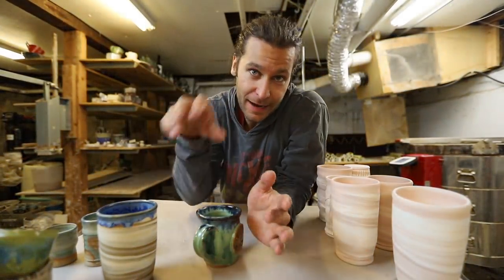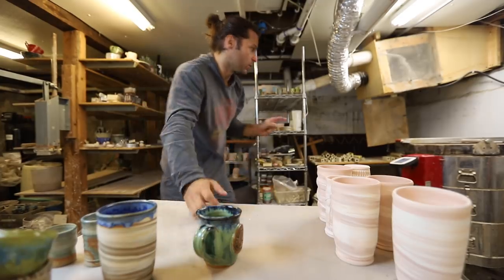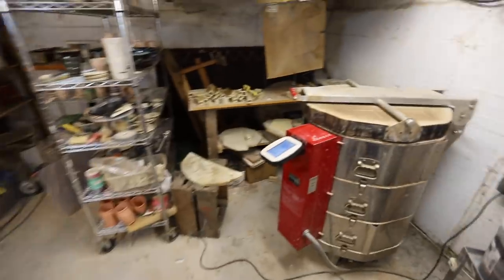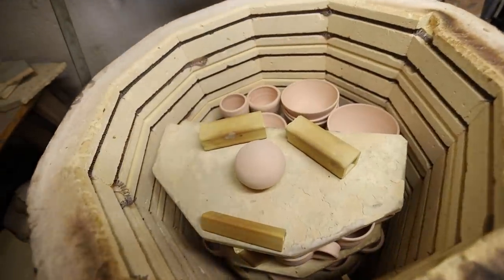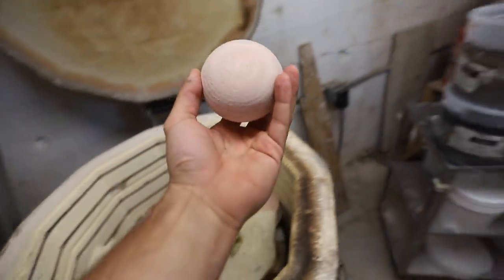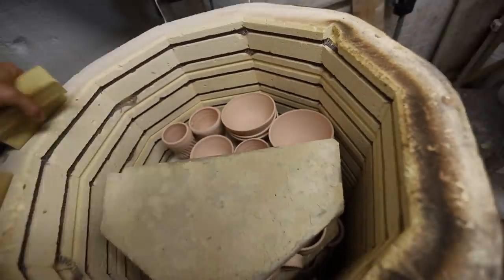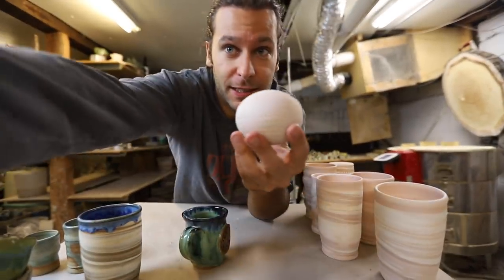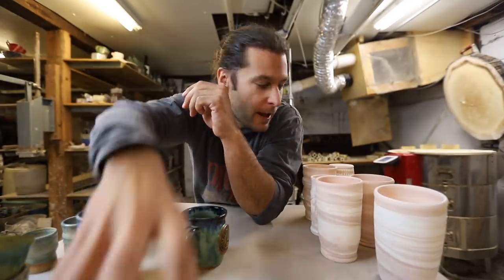We are back after a couple of days. The kiln went up to 1,828 degrees and came back down — it's now at 120 degrees. Let's go check it out and see if this thing blew up. I'm so nervous. Oh, it's still a little warm. There it is — it did not break! And how are these mugs underneath here? Totally fine. These were totally wet when we put them in. All good. Does that settle it? Does that settle it that air pockets will not blow up your clay? Because we basically just fired a giant air pocket. It didn't blow up in the kiln.